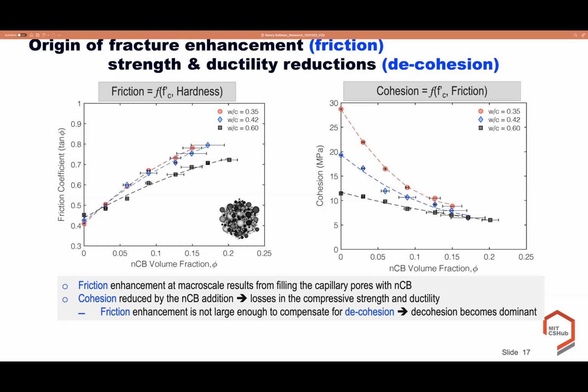And now we answer the last three questions. Why is the compressive strength reduced? Because of the de-cohesion. And why is the ductility reduced? This is also due to the de-cohesion, as the sole energy dissipated in plastic deformation is due to the de-cohesion. So friction doesn't dissipate any energy. And why do we have the enhancement of the fracture toughness? Due to the enhancement of the friction coefficient of the material.